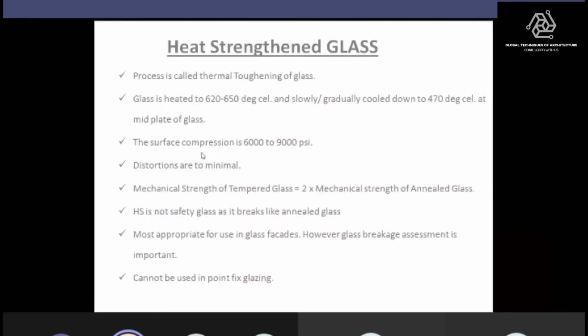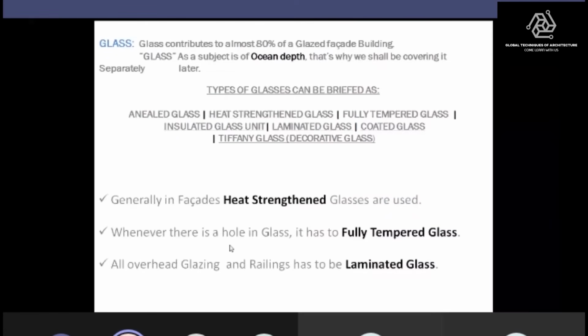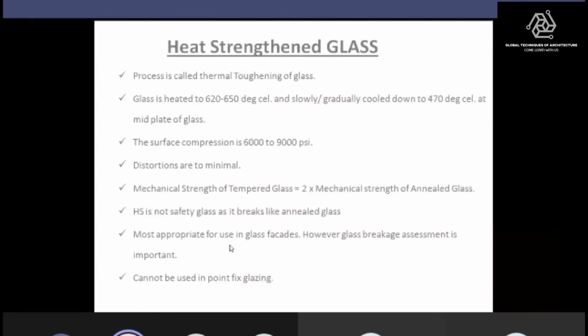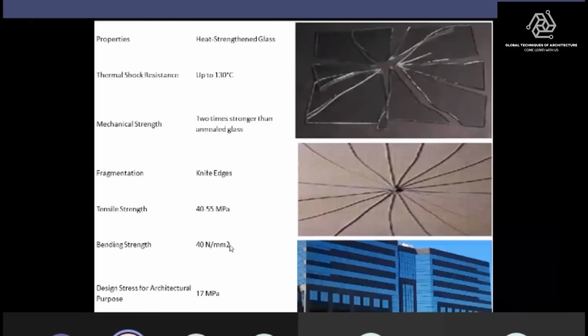But the only drawback is since it has no strength pertaining to the holes made, wherein spider glazing is to be used, like the last point we said, it cannot be used in point fix glazing. Cannot be used, because for the drill hole, as we said, for a drill hole we need FT glass. So heat strengthened glass has some beautiful mechanical properties. Thermal shock resistance is up to 130 degrees, 2 times stronger than annealed glass, but the only issue is it breaks down in knife edges.